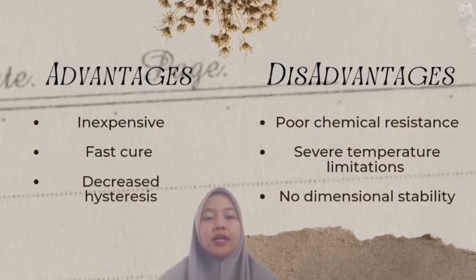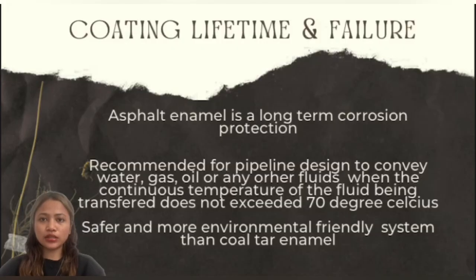The advantages of asphalt enamel coating are that it is inexpensive, fast cure, and decreases hysteresis. While the disadvantages are poor chemical resistance, severe temperature limitation, and no dimensional stability. Asphalt enamel is a long-term corrosion protection. It is recommended for pipelines designed to convey water, gas, oil, or any other fluids when the continuous temperature of the fluid being transferred does not exceed 70 degrees Celsius. It is a safer and more environmentally friendly system than coal tar enamel.